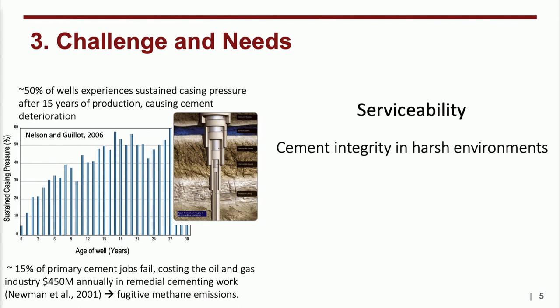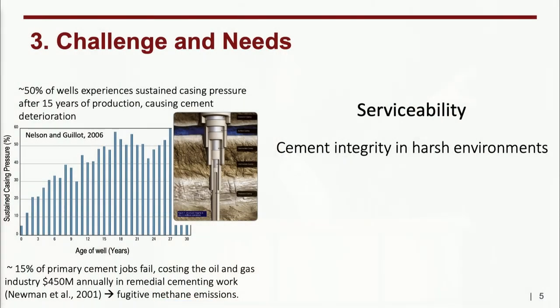The third challenge is serviceability. There are many applications, from aerospace to the subsurface. We need to make sure that the integrity of the cement remains as it is for a long time, especially if we're dealing with a harsh environment. Just as an example, in this plot, derived from the analysis of 18,000 wells in the Gulf of Mexico, I'm showing that 50% of the wells experience sustained casing pressure, so excessive pressure on the casing of the wells, after just 15 years of production. And about 15% of primary cement jobs fail, costing the oil and gas industry more than $450 million annually in remedial cementing work.